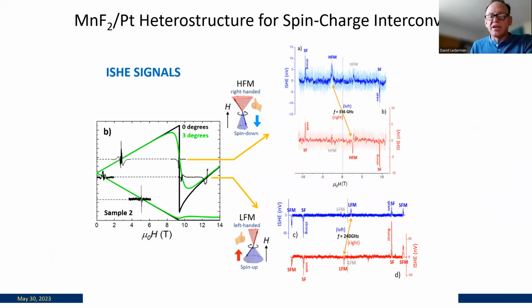You just have to mount the sample really carefully, because it's essentially in a waveguide. You can see, for example here, I didn't talk about this, but our data shows that we were not aligned perfectly. So to analyze the data, we have to take into account that the modes do not look like the black line, which is when the field is perfectly aligned with the c-axis,